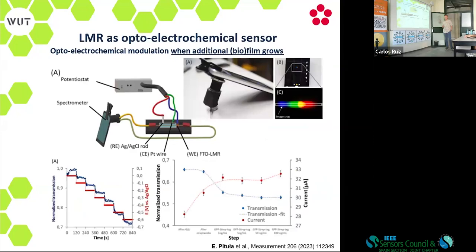Okay. So we apply a very simple device. That's a smartphone converted into a spectrometer. There's some adapter, there's some grating slide, and there are fibers. Input fiber and output fiber, electrochemical cell, potentiostat here. So you can see when you apply voltage, we can monitor the change in transmission. So by applying voltage, we see optically the changes. And when some biomaterial appears on the surface, electrically, obviously, we see it. Yeah? So that's the electrical response, and the current increases, but the optical response also changes. So with the smartphone, we can optically identify electrochemical interactions.